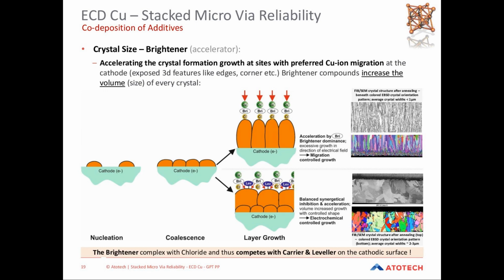And this is then also the mechanical best structure of electroplated copper deposits. This we only show you to give you a better understanding that these additives for sure adsorb on interfaces, especially during nucleation of the electrolytic copper plating process. They are required to achieve the copper quality for best ductility and very good tensile strength. On the other hand, for sure, we should take care that they are not built into the copper deposit and that they do not remain on the interface by too strong adsorption.